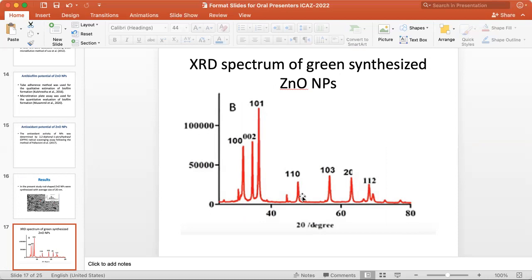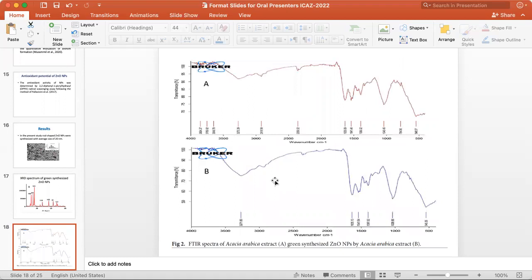And in the XRD spectrum, well-defined diffraction peaks having two theta values at 31.72, 34.39, 36.23, and 47.44. These diffraction peaks confirm the presence of zinc oxide nanoparticles.